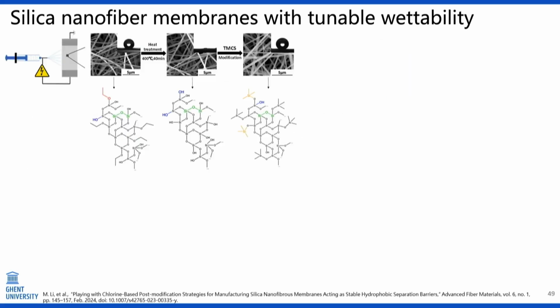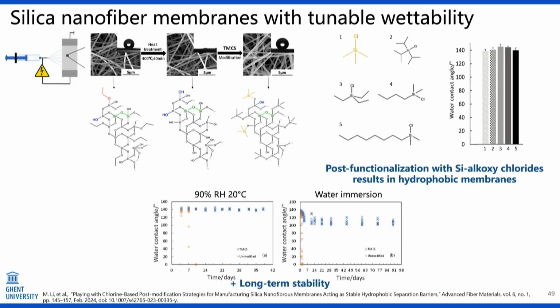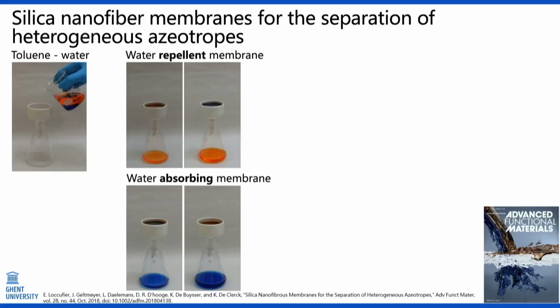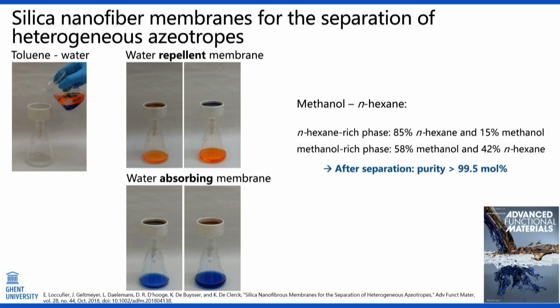But if you want them to remain hydrophobic, you can functionalize them with a hydrophobic precursor, and then you have a long-term hydrophobic performance. So we can make both long-term stable hydrophobic, but also long-term stable hydrophilic membranes. And it are then these membranes that we can use for separation of solvents. And why are silica interesting here? Because they're not dissolved by the solvents, and we can use them for less harmful solvents, and we use them here to separate heterogeneous azeotropes such as toluene, water, but also methanol, hexane mixtures. And by just pouring over, so we don't need any energy, it's a very low energy consuming process, we can have a high separation with a very high purity.